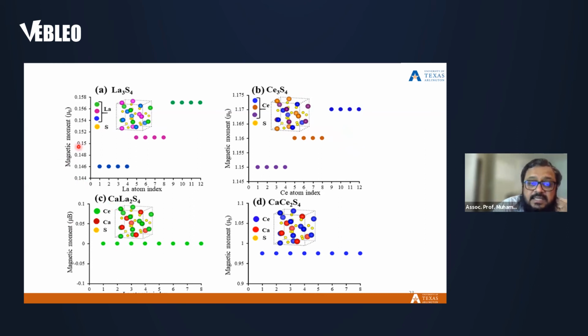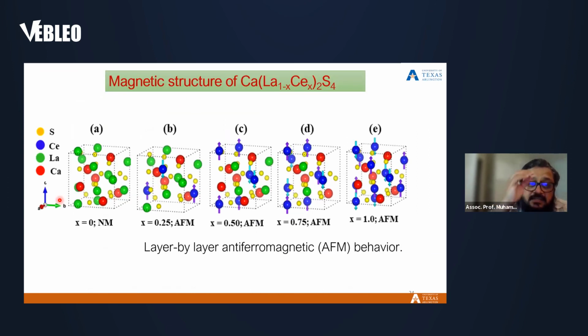Another point to be noted: without calcium, in lanthanum sulfide, these lanthanum have spin magnetic moments, and there are 12 lanthanum atoms, and they can be organized in 3 different groups. Similarly for cerium, when we put calcium in there, we choose one of these groups to replace lanthanum by calcium, and we have found that configuration is more favorable than random distribution of calcium within the structure. Similarly, when we start putting cerium in calcium lanthanum sulfide, we started to substitute cerium by taking group by group. And again, we've calculated stability, both the site selection method versus random distribution. This site selection method seems to give better or more stable structures.